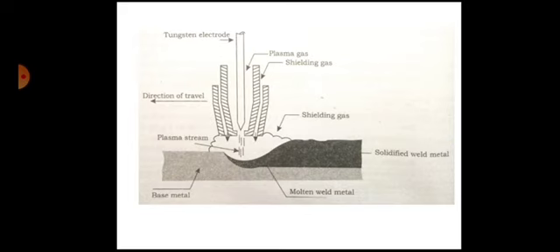Mostly, in this plasma arc welding, DCSP, direct current straight polarity, is normally used with currents in the ranges from 50 to 350 ampere at a low voltage of 27 to 30 volt.